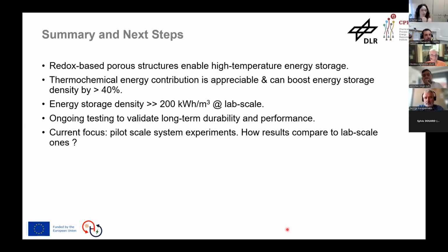So to summarize, redox active porous structures offer a promising route to high temperature energy storage. The thermochemical contribution can increase total energy density by over 40%, with lab scale tests exceeding 200 kilowatt hours per cubic meter. We are now validating this at pilot scale, focusing on long-term durability and system performance. Our next steps will include comparing pilot results with lab data to assess scalability and commercial potential.